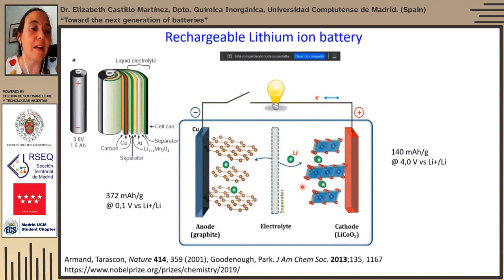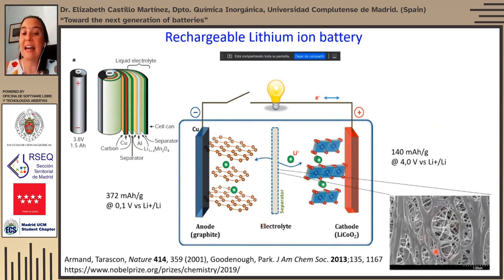So if we were to look at one of these cylindrical batteries from inside, we will see that they actually consist of a roll of many thin films stacked one on top of each other. These thin films are a copper anode current collector, then the active material, the anode itself, which in the case of commercial lithium-ion batteries is graphite intercalated with lithium, then a polymeric separator, which has a microporous structure, and it's designed so that if the temperature rises because of some short circuit event, the pores close, and then the short circuit can be stopped. Then the layer of cathode material, which in the first commercial lithium-ion batteries was lithium cobalt oxide, and then the aluminum current collector on the cathode.